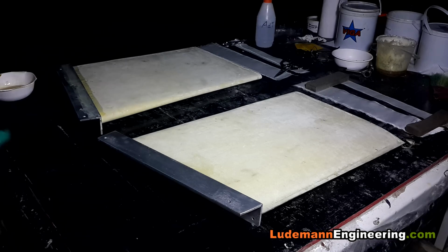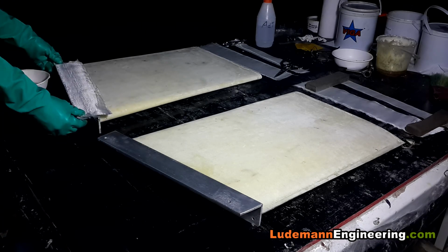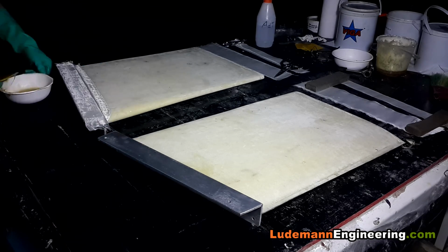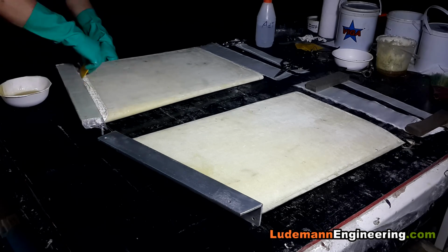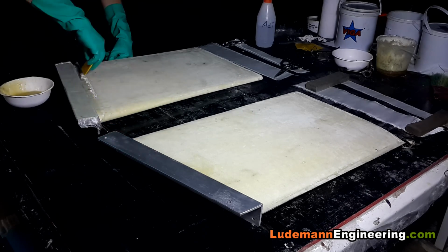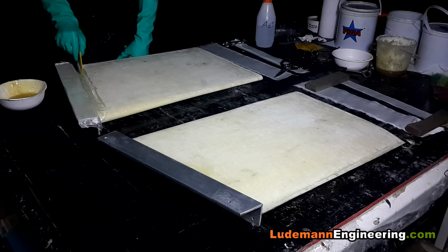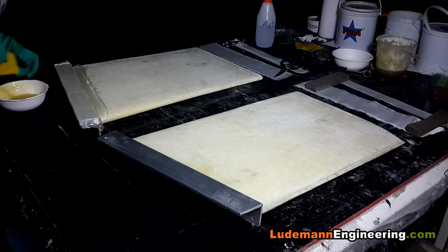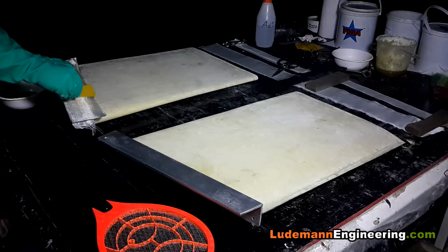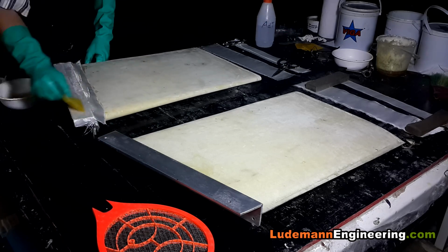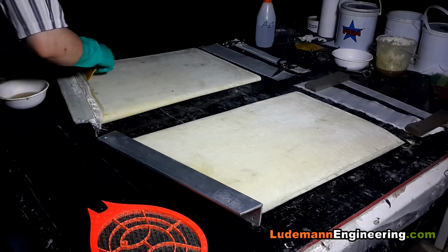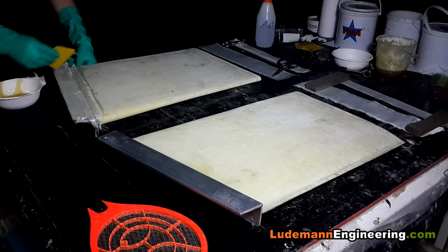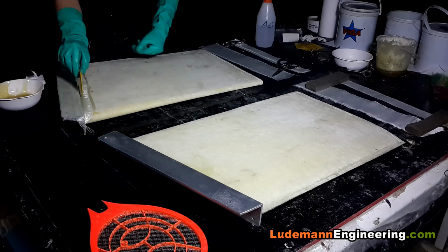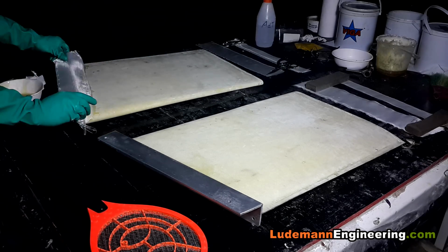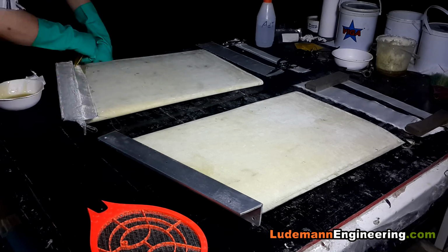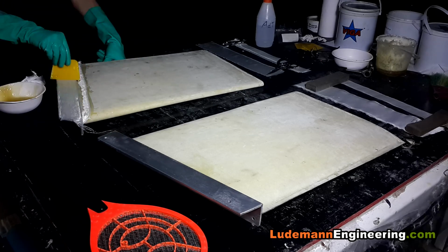Now we're going to reinforce the joint between the bottom of the end plate and the aluminum angle. It was glued on there earlier, but now we're going to use, I believe, 4-inch wide fiberglass tape. And we're covering the entire area of the aluminum to get the maximum area to stick the tape onto. You don't want that to delaminate because this will be a high stress area when it's actually being used on the race car. So I think about 4 layers of cloth here.